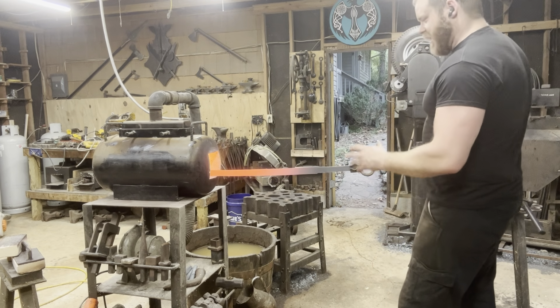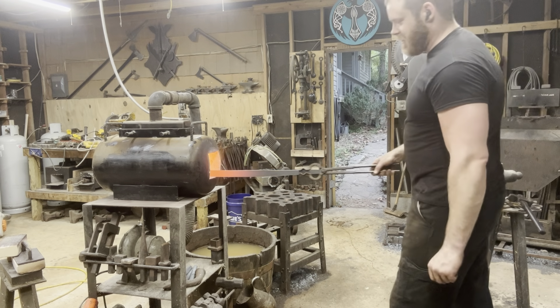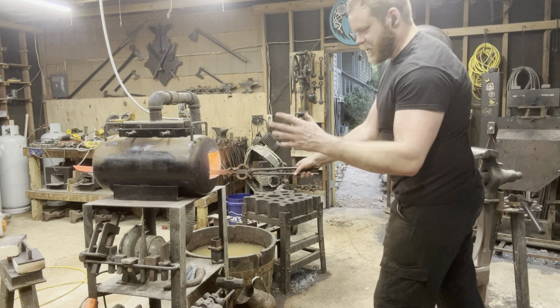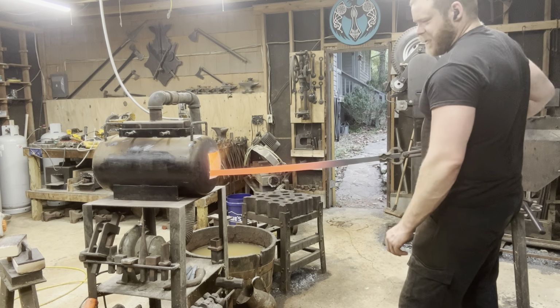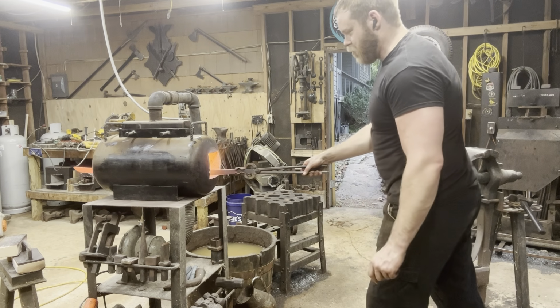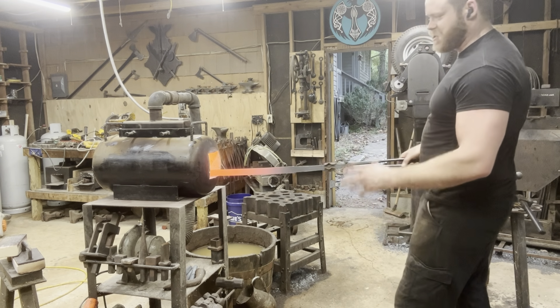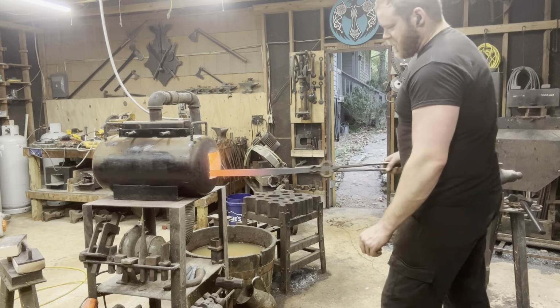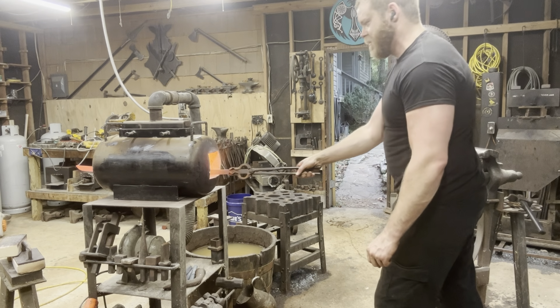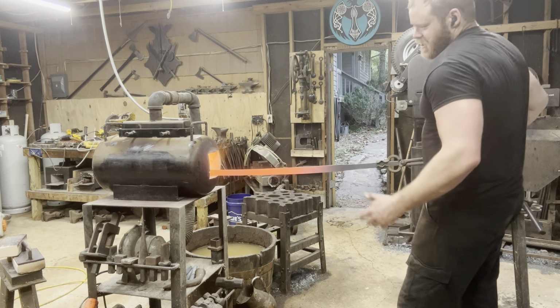But once I get a heat I'm happy with, I'll sit it in the vise facing up to cool off and let it cool in still air on its own. You don't want to lay it flat on your anvil or the floor or anything like that, because if one side cools faster than the other, it could end up warping on you during the quench, and you just want to avoid that if you can. Nothing to it really.